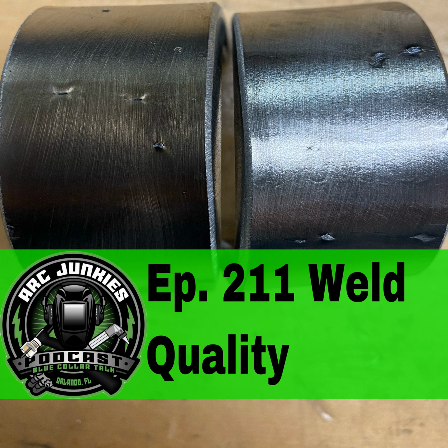Take the backing strip off, grind the root face down, prep it for a guided bend test, and then bend it. And this is where I typically see your slag inclusions come back up, that you said we were going to weld over top of, and we'll just burn it out with 5 to 10 amps more. I see lack of fusion in there, lack of penetration. This is where all this stuff comes to fruition. So just because the weld passes visual doesn't mean it's still a good weld.